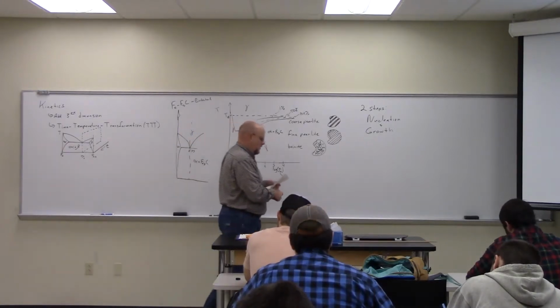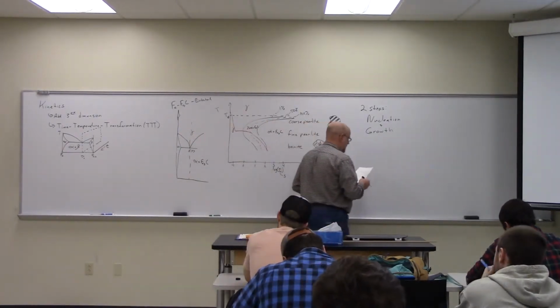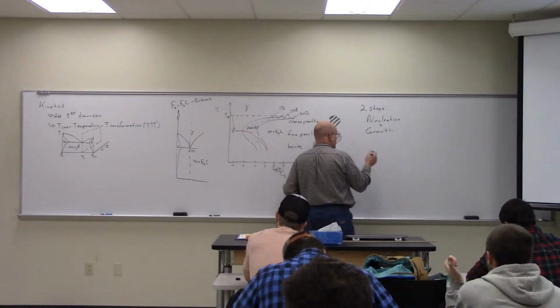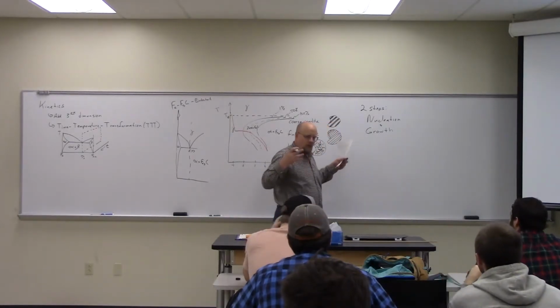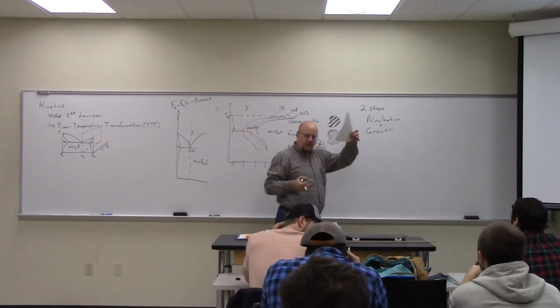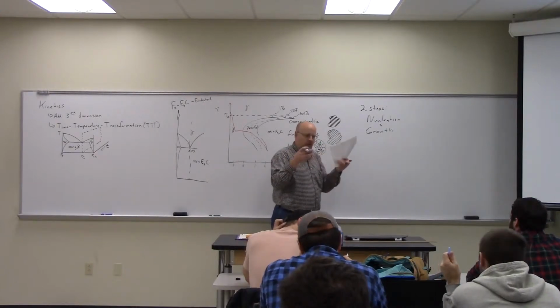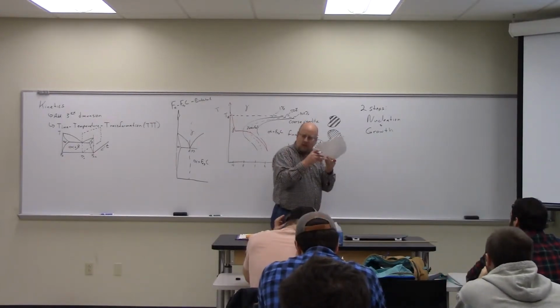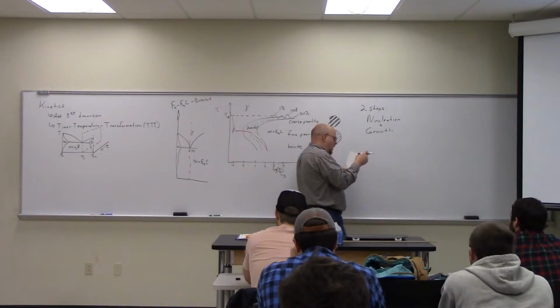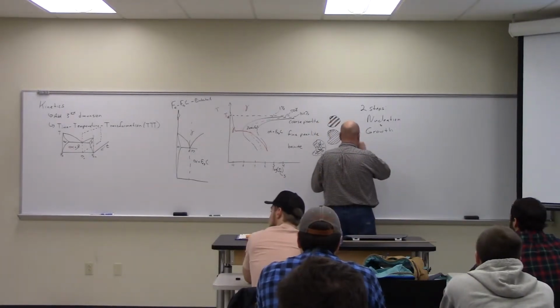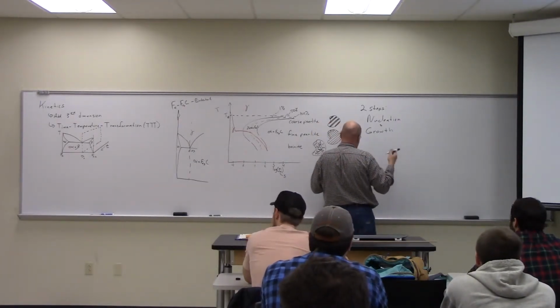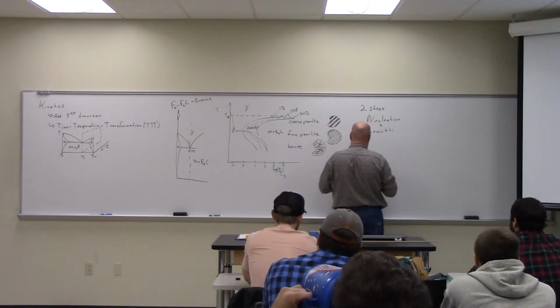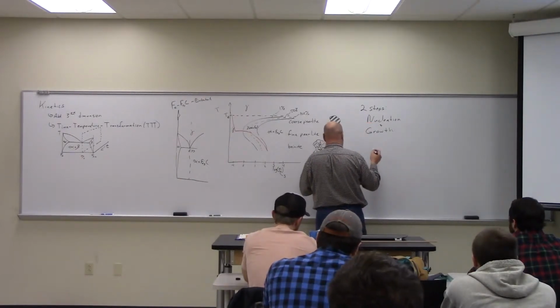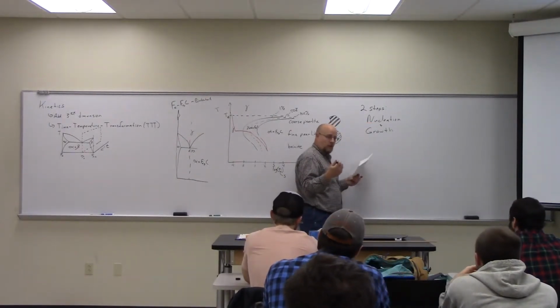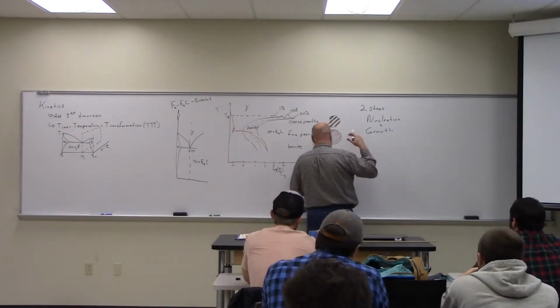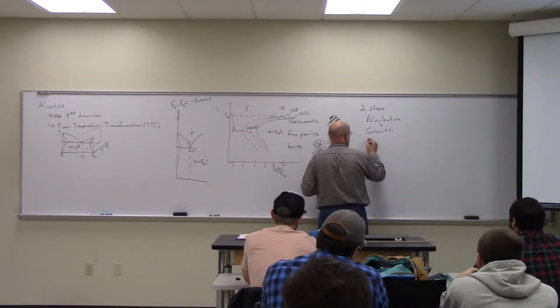So let's look at nucleation first. We have local diffusion that governs: all these atoms have to come together, diffuse through whatever's there, to nucleate a particle. So they have to coalesce. As I said, things like high energy regions, like the grain boundaries or the surface, as Colin pointed out, it's going to happen on the surface. You have higher energy on the surface. So there are two driving factors.